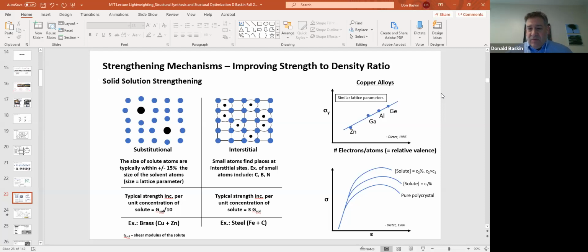And the strength increase with this is actually much higher. You actually get 3 times the shear modulus per unit concentration increase of the solute. An obvious example of this one is steel. Steel is an alloy of iron and carbon. The carbon sits at the interstitial positions between the iron atoms. So that's an increase in strength associated with this interstitial method, solid solution strengthening.